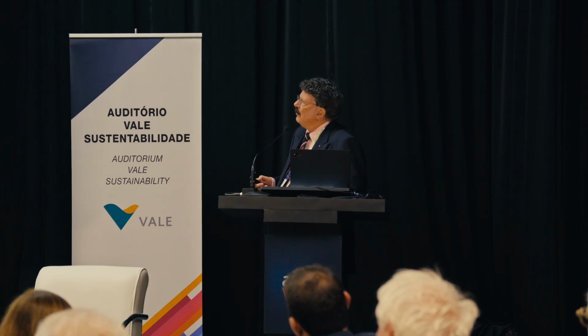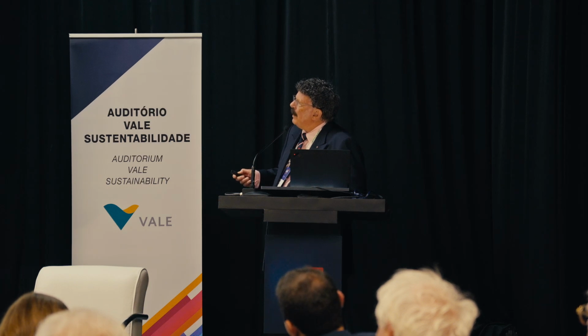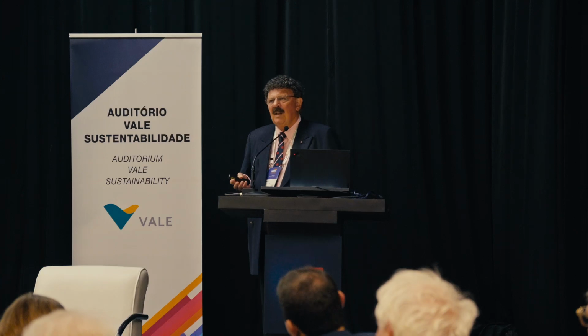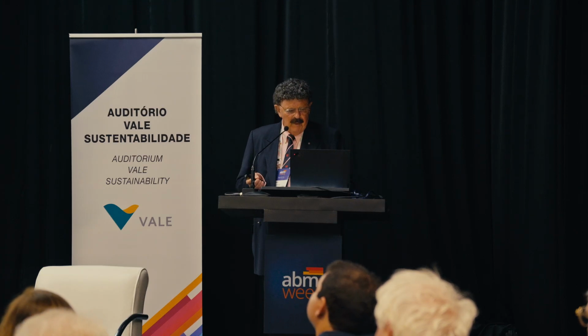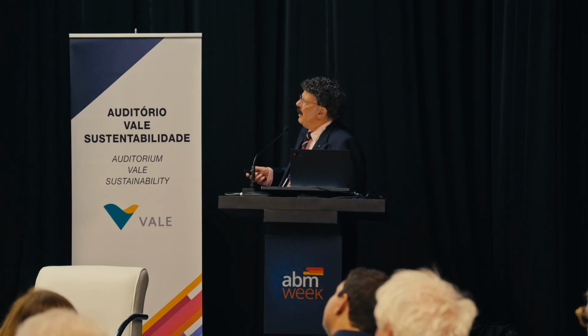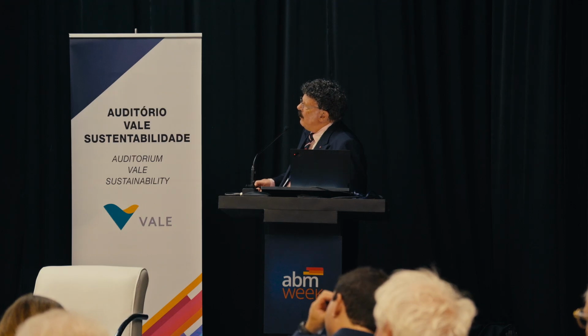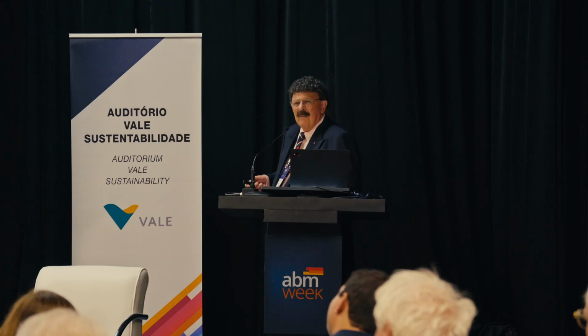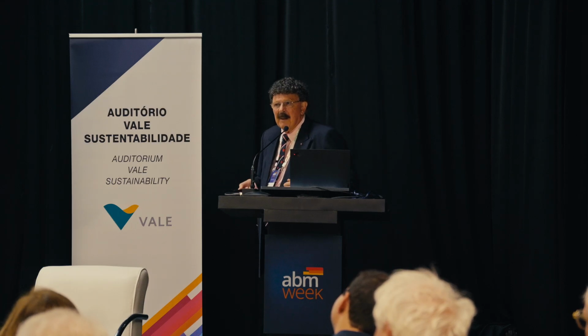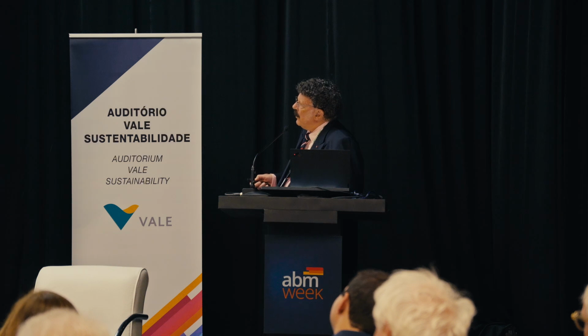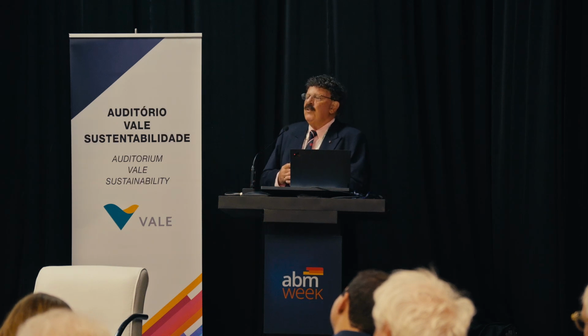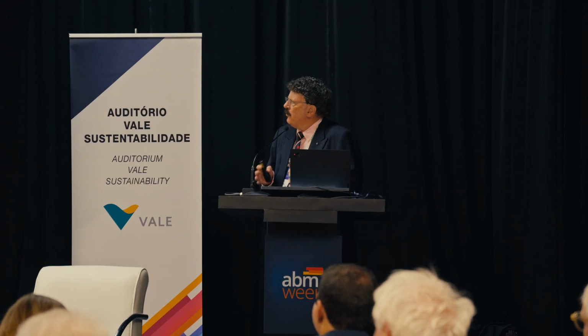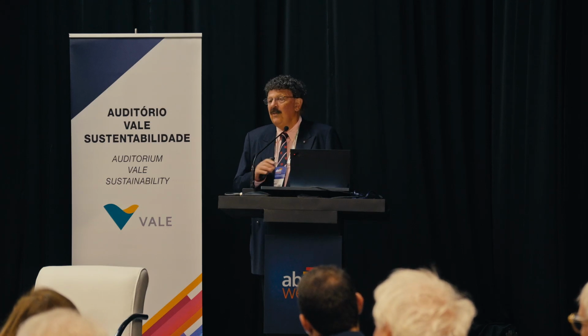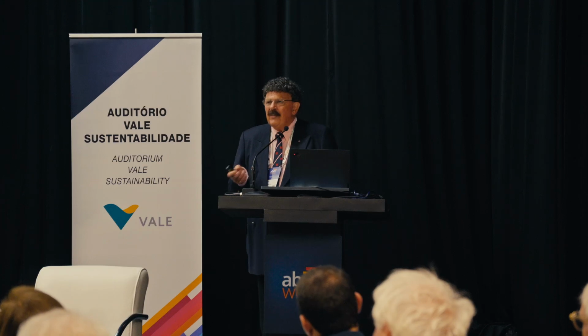Fascinating, really interesting material. And you can see the toughnesses are highest probably at room temperature, but they're still extraordinarily high for a BCC material at liquid helium temperatures. So the mechanisms are a little bit different. We get formation of an omega phase down at this very low temperature, 20 degrees Kelvin, and we get cracks that are jumping over boundaries. There's a little bit of bridging here, which is like a ceramic mechanism, but this is associated, we think, with where the cracks forming the boundaries is where the phase transformation to the omega phase forms. So it's a very, very interesting material. We have a paper which is in review now to try and understand this, but it's quite different to anything we've seen before.